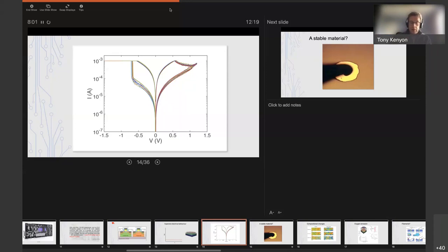So you're probably looking at selecting metals from a relatively small group. It might be metallic compounds like titanium nitride. You may be looking at tungsten, titanium, ruthenium, and a handful of others, and avoiding copper and silver and others that may diffuse. But it is really critical to think about what that electrode material is. It's also critical to think about what the nature of the interface looks like between the electrode and the oxide, so whether there are a lot of defects there, whether it's smooth or rough.